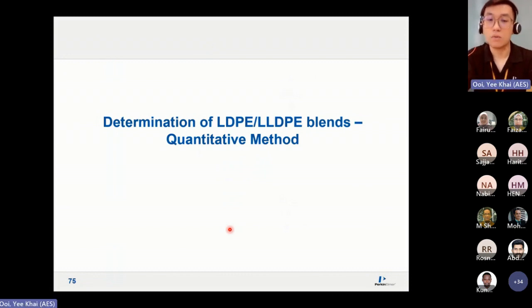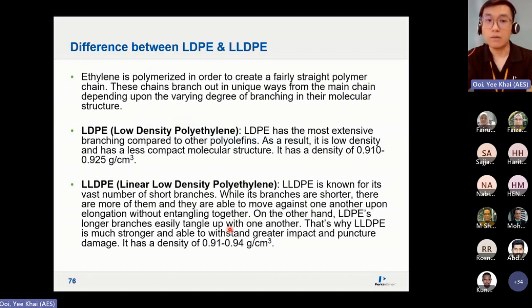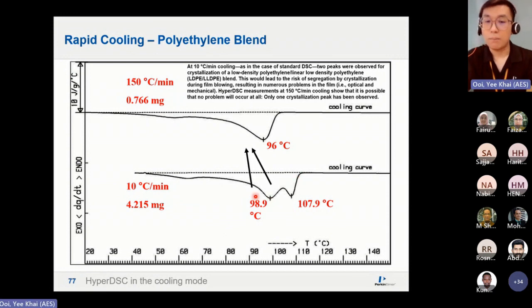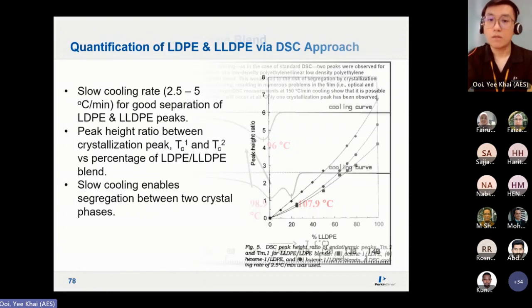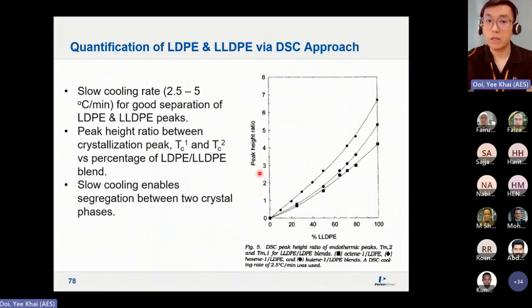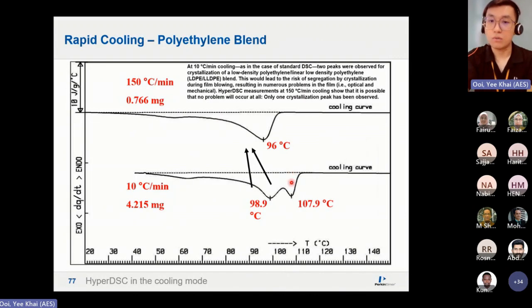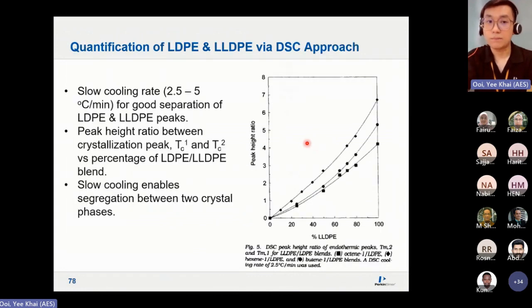Then you can also use DSC for quantitative analysis of different polymer blends or copolymer blends, like LDPE and LLDPE. LLDPE and LDPE actually have different crystallization peaks. So if we cool it down very, very slowly, we can allow them to segregate more completely. We can then plot a calibration curve based on the peak height ratio of LLDPE and LDPE, that is, the percentage of LLDPE inside versus the peak height ratio between these two peaks. But to allow complete segregation, you need a very slow cooling rate to get good separation of LLDPE and LDPE.